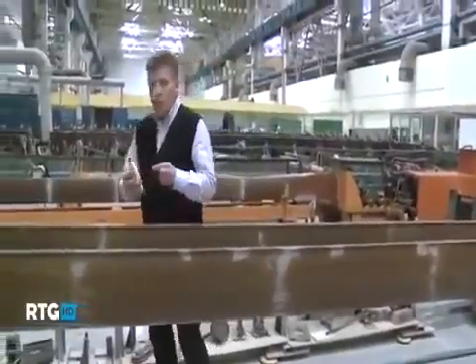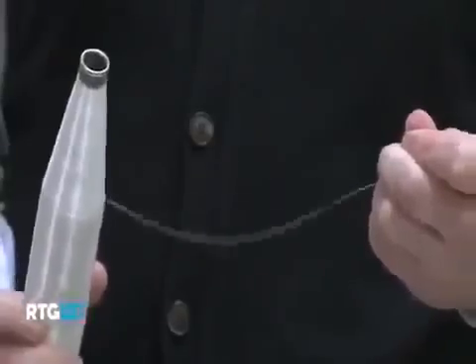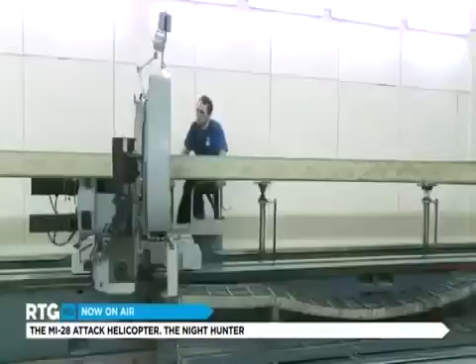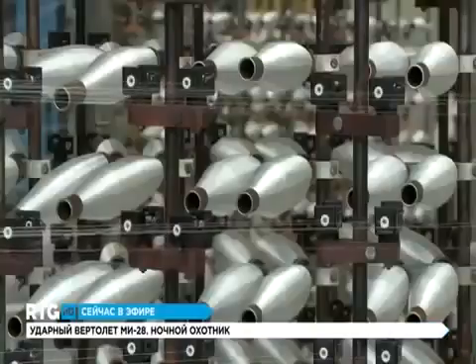Longerons are made of fine thread, which is very strong. It's made of 4 fiberglass filaments woven together, which are 7/1000th of a millimeter in width. With a length of almost 8 meters, the longeron weighs less than 100 kilograms. And it's also quite flexible. It's hard to imagine that it's made of fine fiberglass filaments.